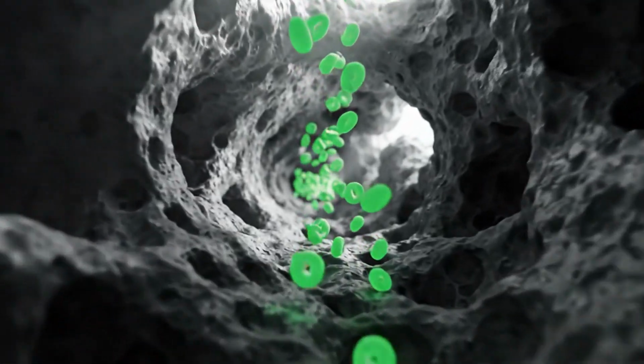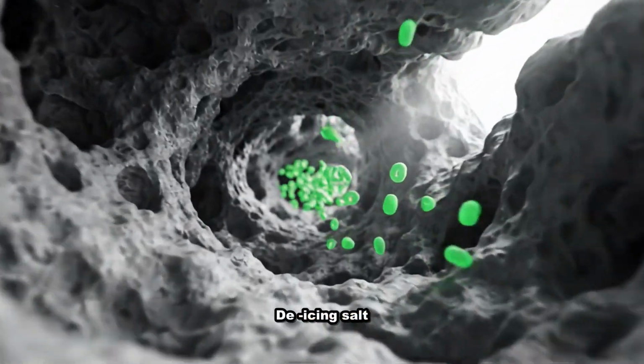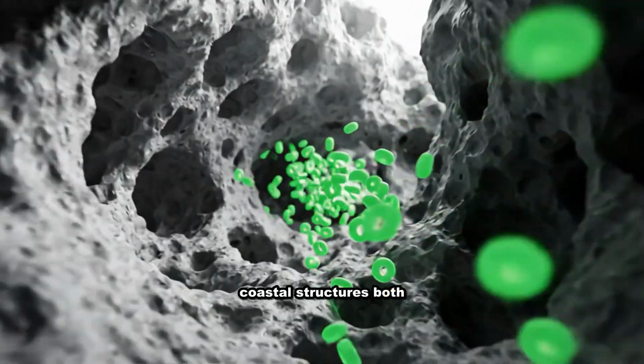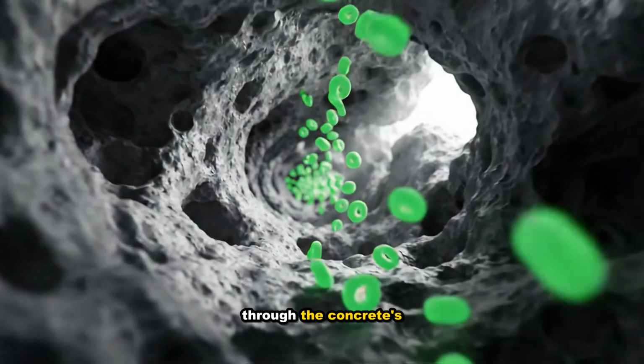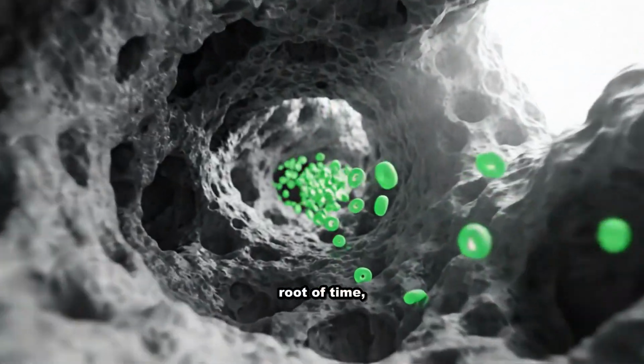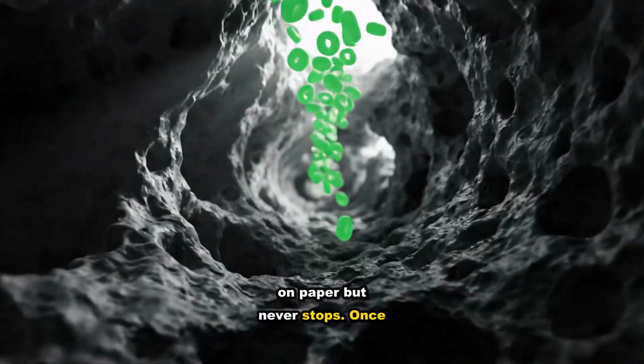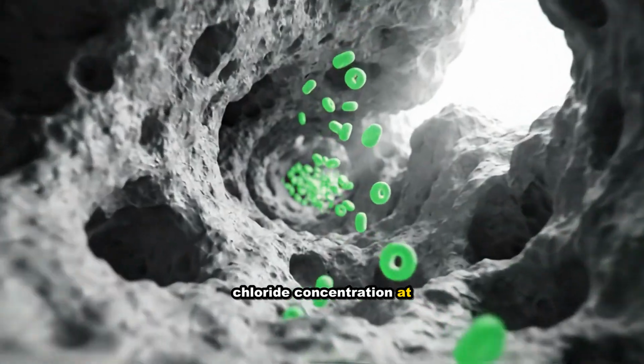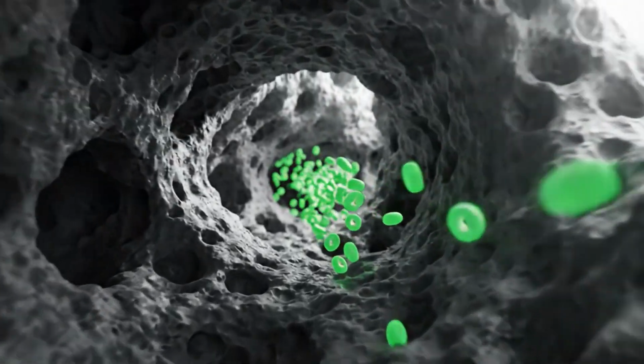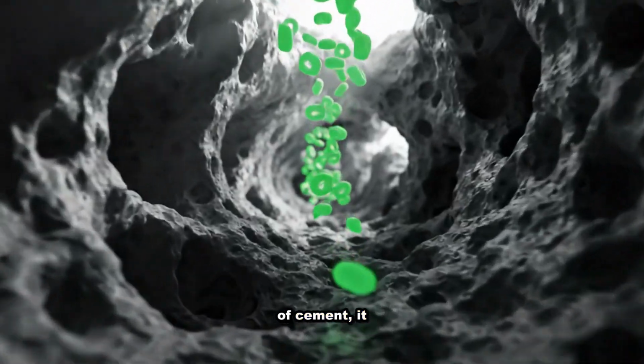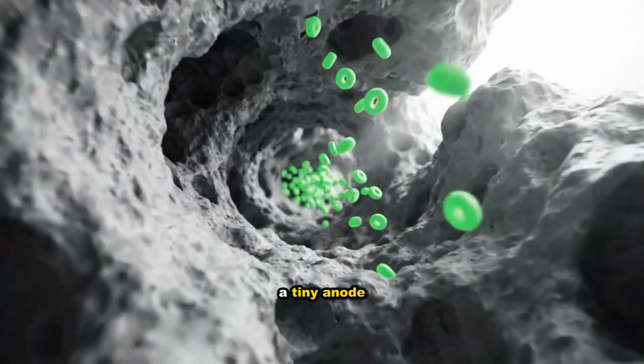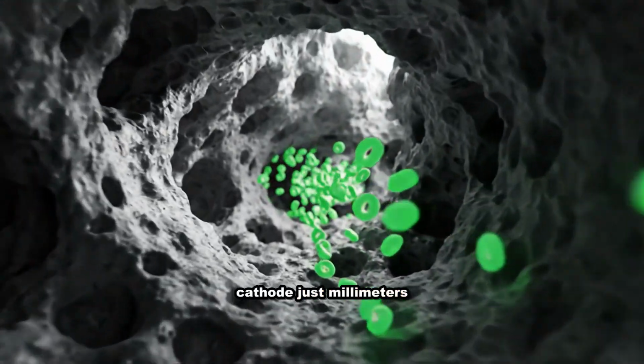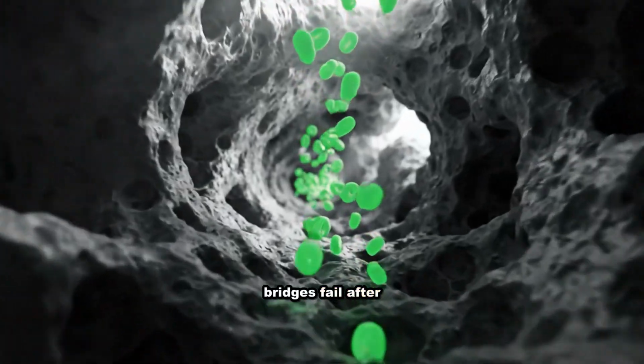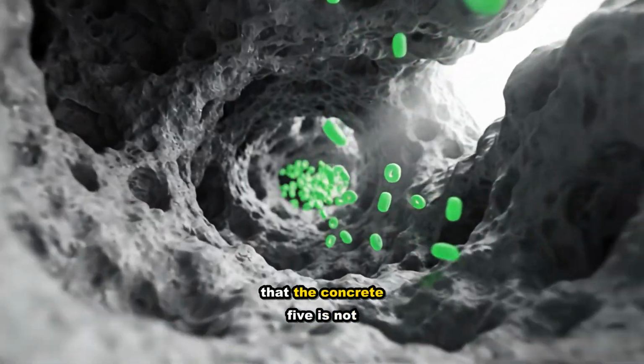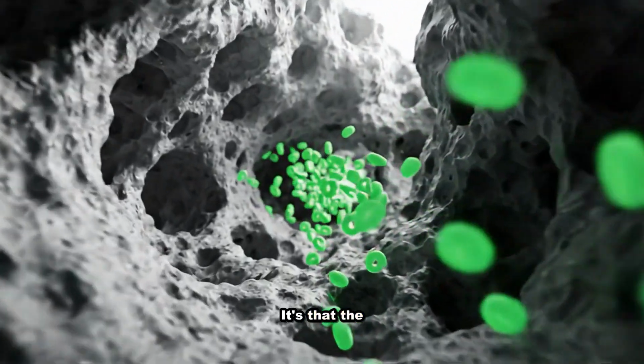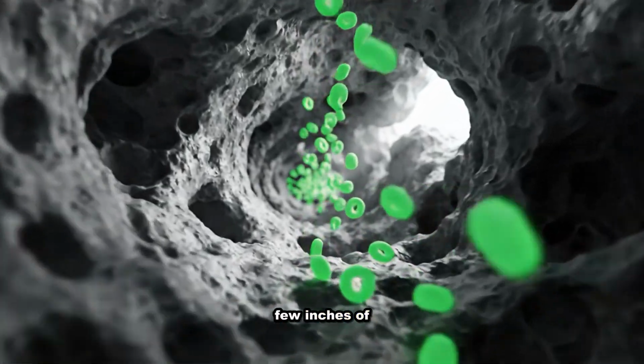Chloride ions are the trigger, and they arrive from two directions. De-icing salt on northern roads and seawater on coastal structures both carry chloride, and those ions diffuse through the concrete's pore network at roughly the square root of time, meaning penetration slows on paper but never stops. Once chloride concentration at the rebar surface crosses a threshold, around 0.4% by weight of cement, it breaks the passive film locally, creating a tiny anode surrounded by a cathode just millimeters away. The reason bridges fail after 20 or 30 years and not 5 is not that the concrete resists chloride forever. It's that the chloride simply takes that long to migrate through a few inches of cover.